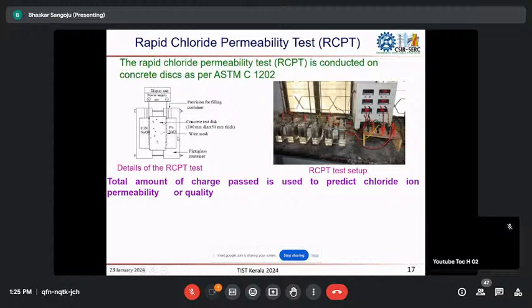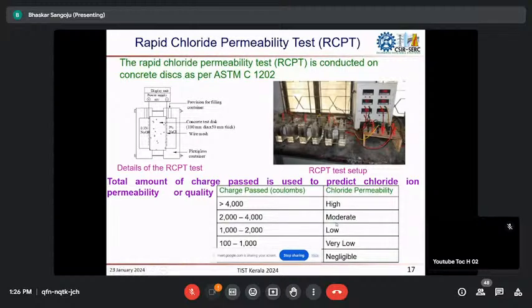So in addition to chloride ions, the ions that are available in the concrete pore solution also try to move and affect the total amount of charge passed. So strictly speaking, it is not only the chloride permeability test; it is just the amount of charge passed. Many other ions that could be available in the pore solution also will contribute a little bit. Otherwise, for relative evaluations, we can very well use this RCPT test.